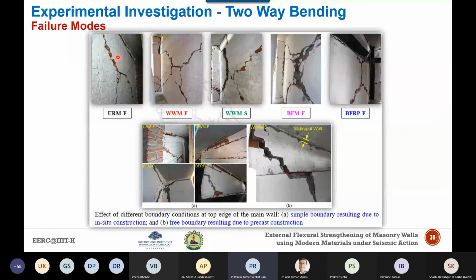However, in this case, the diagonal cracks did not originate directly from the corners of the test wall. Now, in case of this welded wire mesh wall, there are 2 cases, one with the rigid diaphragm, another with the flexible diaphragm. Here you can see that the cracks are developed parallel to the horizontal bandage, and the wall has divided into 2 distinct zones.